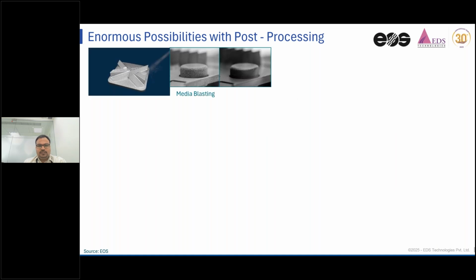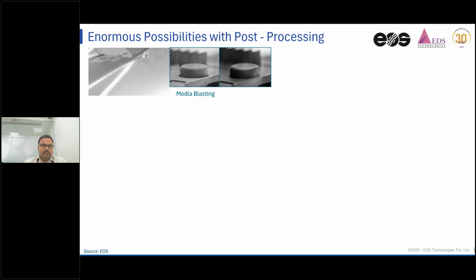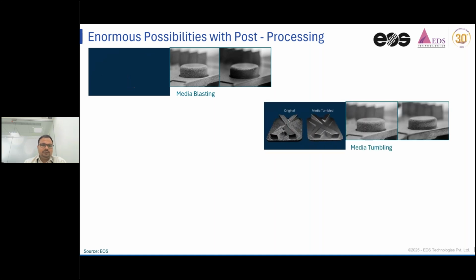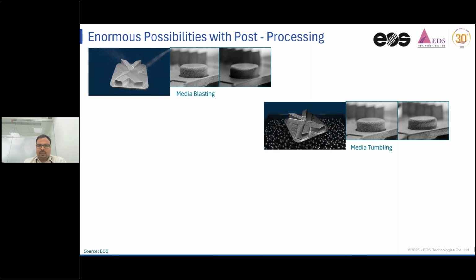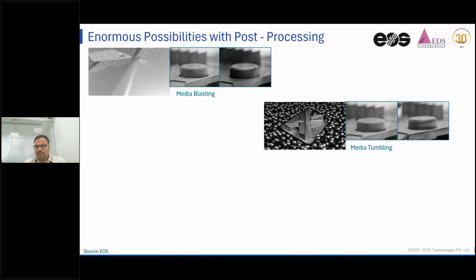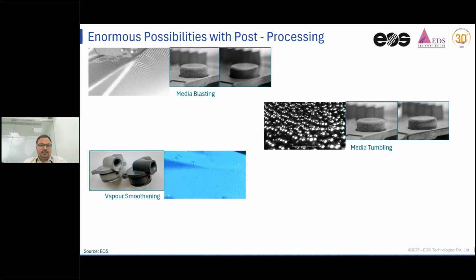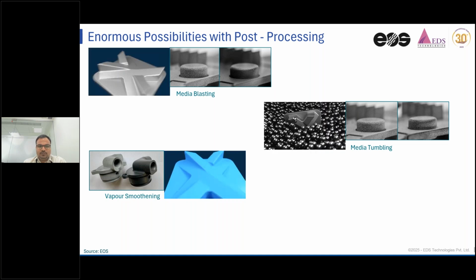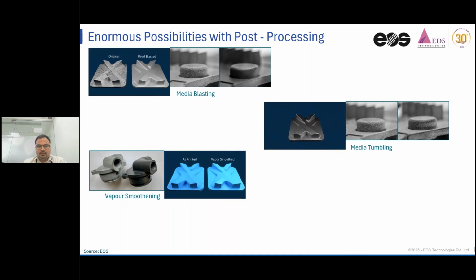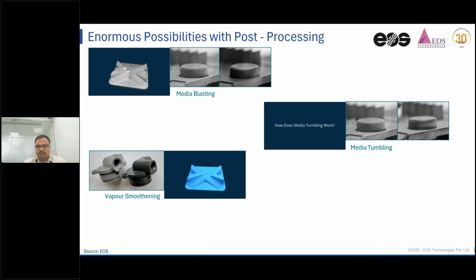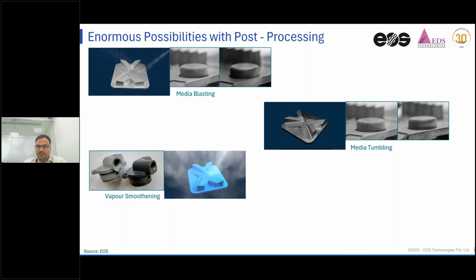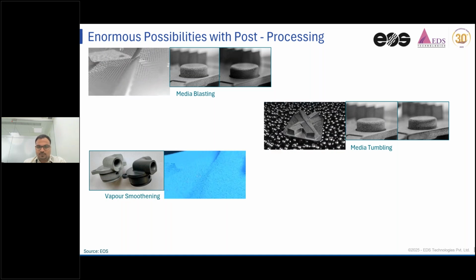There are enormous possibilities with post processing. Once you get the part, you can do media blasting. You can use any media, for example glass beads, to smoothen the outer surface, and you get your finished component. You can do media tumbling, in which you put your part in ceramic media or any other tumbling media to smoothen the outer surface. And you can also do vapor smoothing of the component in an alcohol base, which smoothens the outer surfaces very promisingly. I'll show you how the finish looks after the vapor smoothing.